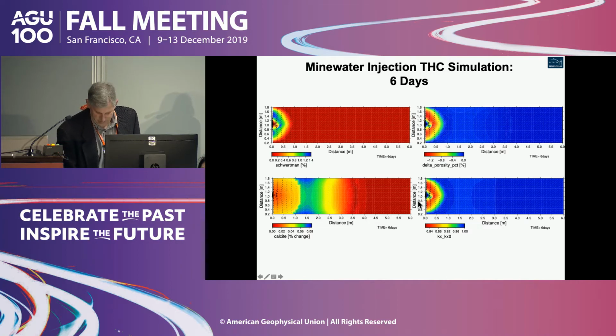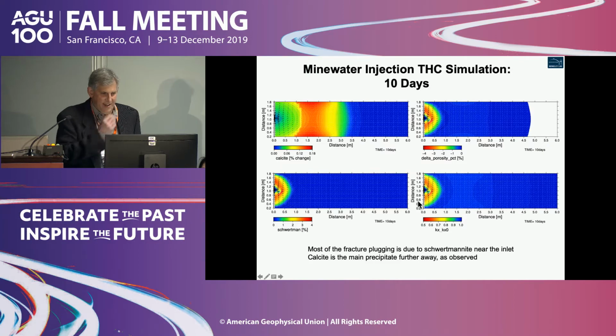in this same region. And then after 10 days, we start getting more calcite. So we still keep seeing calcite out here. We're dissolving it near the inlet. The porosity keeps dropping. That's about a 4% drop in porosity. Now we have about a 50% drop in permeability right near that inlet. And you can see this band of schwertmanite, it's actually pretty strong, about 4%. So we're basically plugging the inlet, but we're also forming calcite further out.